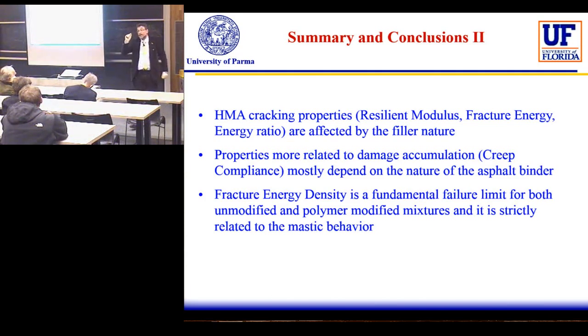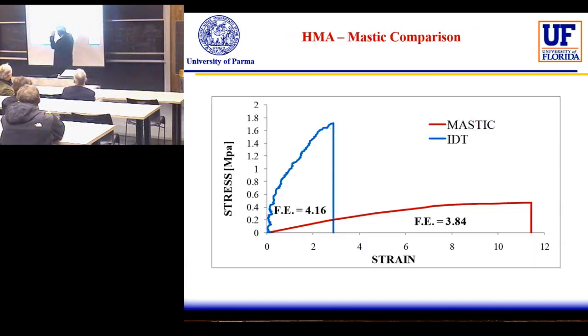The idea is to analyze the material locally, to have the first fracture and consider the material already damaged, even if the general specimen is still efficient, because we are not at the point of the peak of the stress-strain curve. In my opinion, if we reach the peak of the stress-strain curve, this is the failure of the specimen. Generally the first crack appears somewhere here, on the curve.